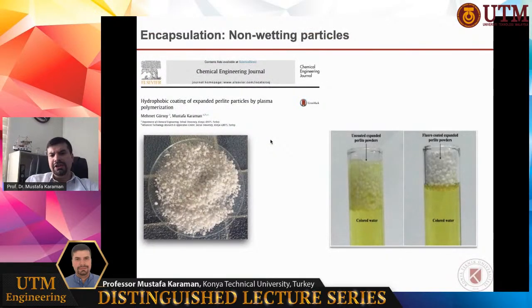So, encapsulation, non-wetting particles. In that study, we used chemical vapor deposition to coat the surfaces of expanded perlite particles. Expanded perlite is usually found in different parts of Turkey. It is a very hydrophilic material. Here you can see in the colored water, the water wets the surfaces of perlite easily. But after CVD coating of a hydrophobic material, you can see at the right-hand side, the fluoro-coated expanded perlite powders are never wetted with the colored water.